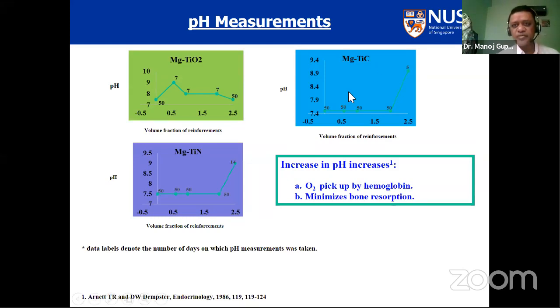On the other hand, for various reasons, if I want to take TiC, then I will go for 2% of TiC in my matrix, and the pH is very stable for all volume fractions of TiC. If I go for TiN, any amount up to 2% is okay, because the pH fluctuation is very limited, and that's what I want in the body—not too much pH fluctuation. So the message here is that every system has its own characteristics.